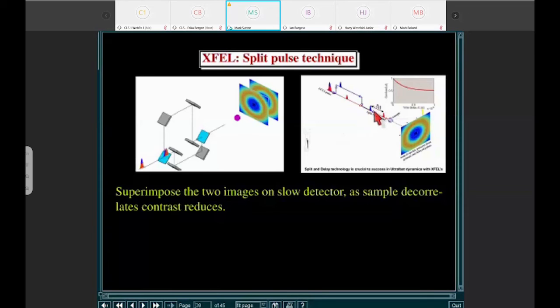If the two pulses are very close together, the two speckle patterns are the same and they reinforce. If the two pulses are far apart and the sample changes in between, then the speckle patterns become uncorrelated. And so simply by measuring the correlation of the speckle pattern that you measure with the sum of the two as a function of time, you can again measure these G2 functions that I've been talking about.